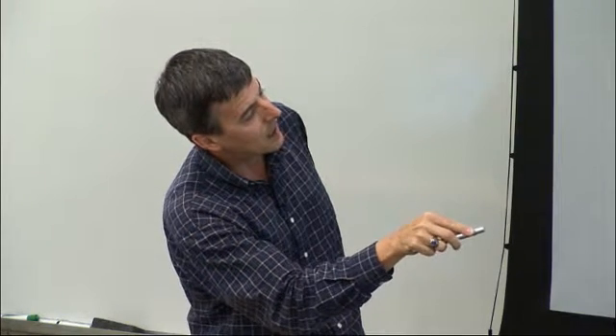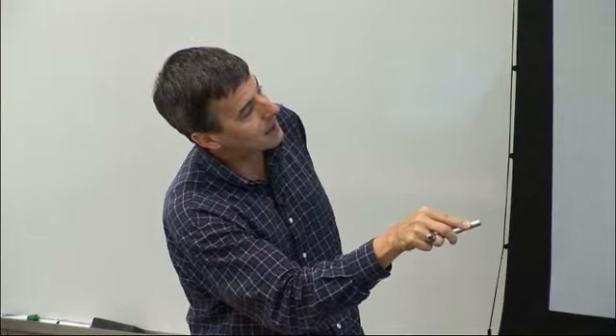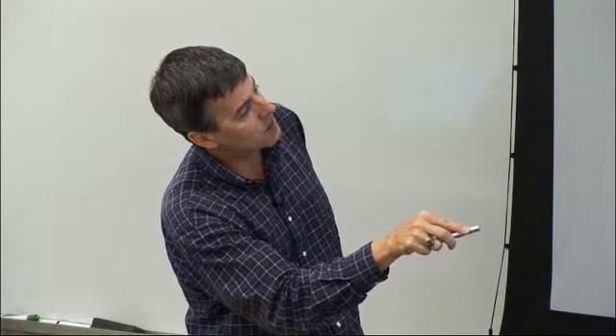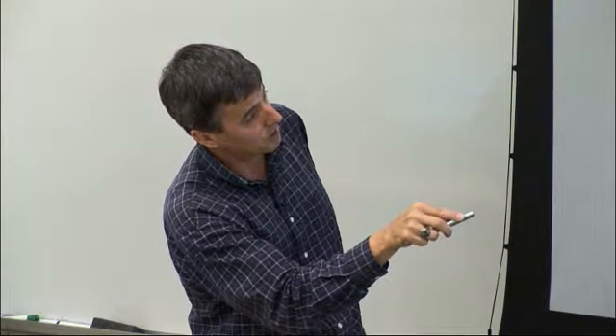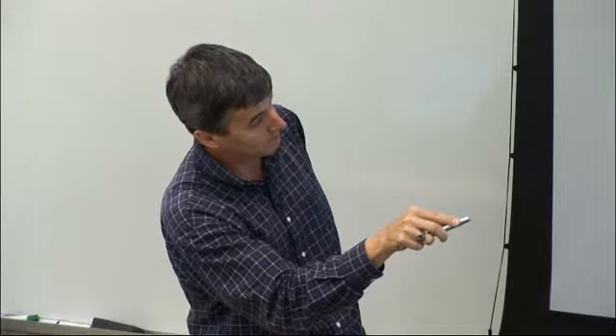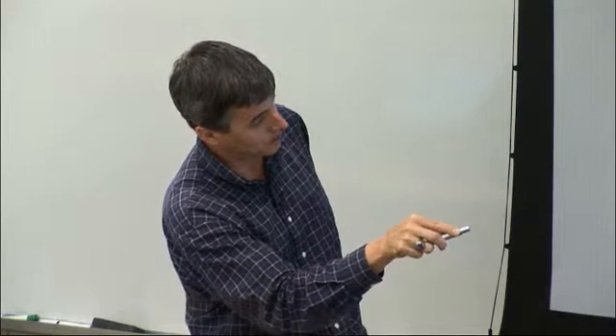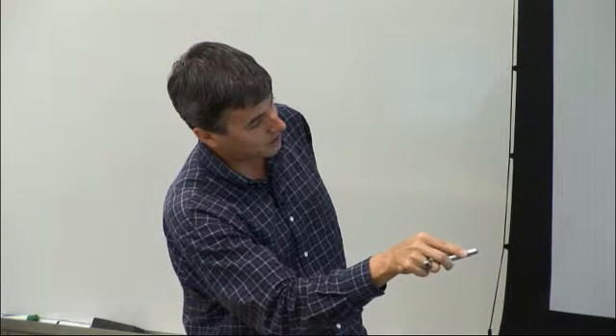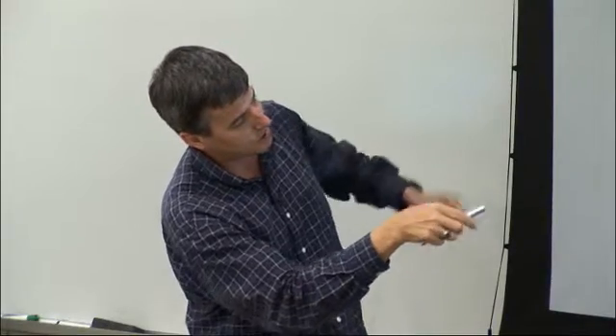The first thing you see is that the measurements along X and Y are quantitatively captured by the modeling. The other thing you see is that the modulus is very much comparable to the epidermis itself, which has a modulus, that slope, of about 160 kilopascal, and you can see it starts to go nonlinear around 15 to 20% strain. So this is actually a better material in some ways. You can stretch it further, but in this small strain regime, it's very well aligned with skin itself.